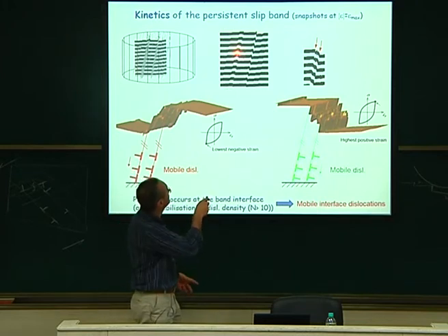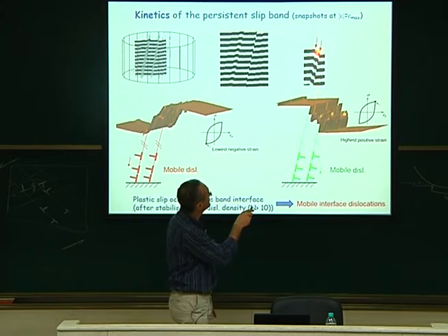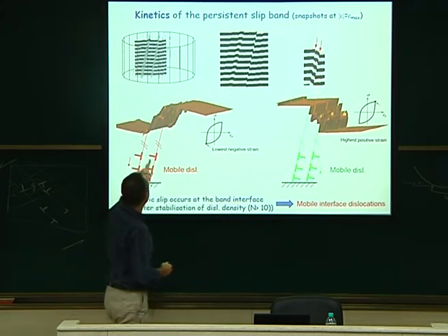The shear is just at the interface between the band and the matrix. Here you have 2 bands. You have shear there and there, shear there and there. Okay. If you zoom, this is how it looks like. The shear is localized at the interface of the band. And this is obvious at the surface.